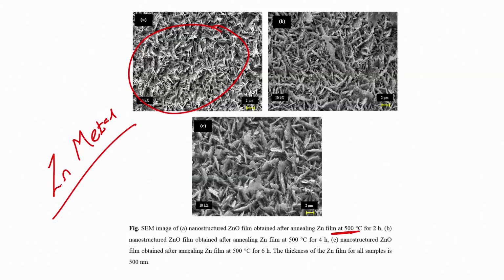But if you increase the time from 2 to 4 hours, this is what you get, and further increasing the time to 6 hours, you get nanoflakes along with a combination of nanowires. This particular structure is better because instead of using a thin film we are using nanostructures, and using nanostructure will increase the surface to volume ratio. So, when the surface to volume ratio is high, the sensitivity of a sensor would be high. Thus, using a metal oxide nanostructure, we can improve the sensitivity of our sensor rather than using a thin film of zinc oxide or a metal oxide material.